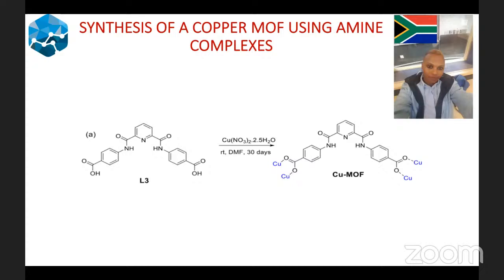But of course, the advantage of your method is that we can retain a high surface area, because when you activate at high temperature, you also tend to distort the MOF, which may then reduce the surface area. With mild activation and your suggested method, we can also increase the surface area of the MOF, which is very important, especially for catalysis. Right. Okay, thank you so much.